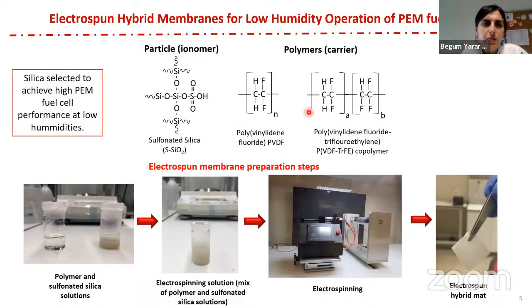I would like to give more detail about the first example. In this study, we produced hybrid membranes using sulfonated silica ionomer as a functional additive, and we also use the polymers PVDF and PVDF-TrFE copolymer as a carrier polymer in the system. Why are we using this carrier polymer? This inert polymer provides higher mechanical strength and controls swelling under fully humidified conditions. For the first time in literature, we use this copolymer for the development of membranes for PEM fuel cell application. You can see the general experimental procedure here.